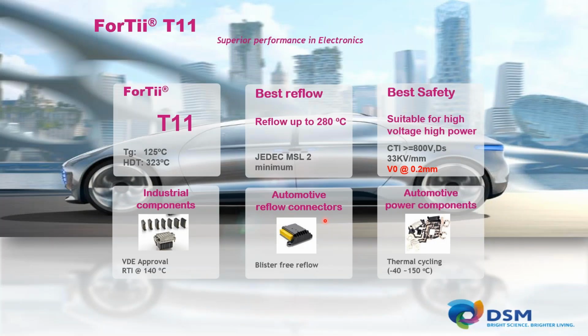So just to recap, our ForTii T11 material is your choice for V0 performance. If you need V0 performance, it boasts a JEDEC MSL level for low blistering, level 2. It's good for reflow processes up to 280 degrees C. Has good robust performance for both industrial and automotive connectors, and CTI over 800 volts.